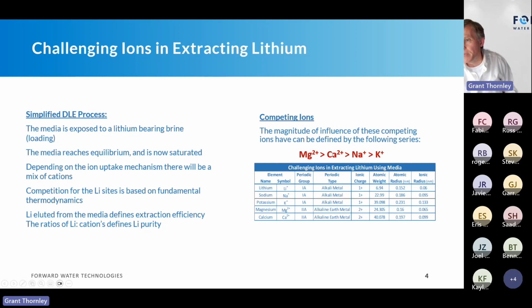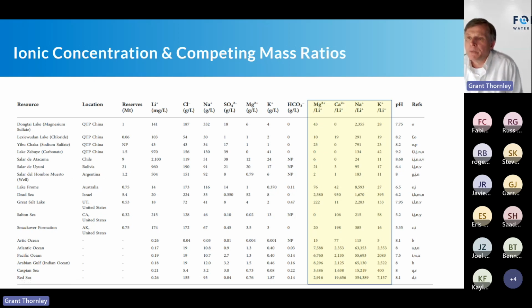You see the bulk or main ions being examined, because these are what's going to challenge the efficiencies. You can look at the alkali metals and alkaline earth metals. When we look at those competing ions, we typically ratio the contaminant against lithium to see what those ratios are. That gives us an indicator of how much of a challenge they're going to be. If it's a low ratio, then great, there's more lithium than that contaminant, and that's going to be easier to resolve on the polishing side. But if the ratio is switched, it's going to be more of a challenge. That's why it's really good to look at what these ratios are.